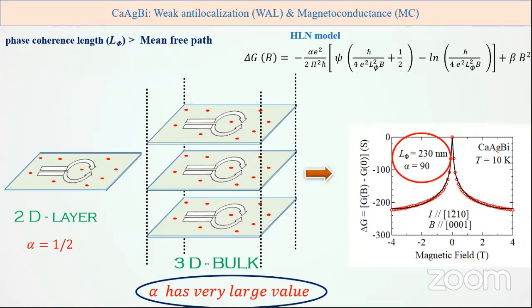Actually, I can tell one thing. We have also a different 3D hexagonal system, ABC type, where we have seen that even up to 8 Tesla we could fit with only the HLN model, not using plus beta B square. That is fitting very well. It means the 2D diffusion is so strong that someone can even ignore this beta B square term.